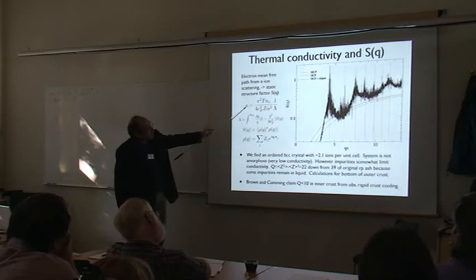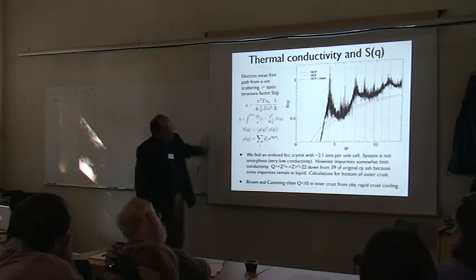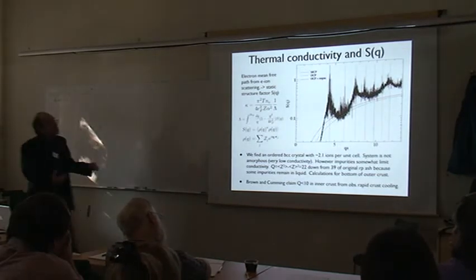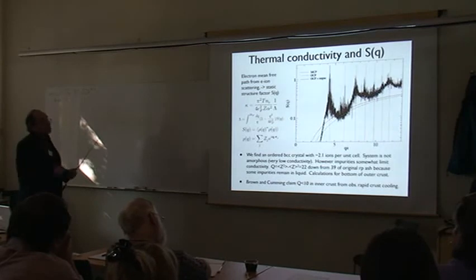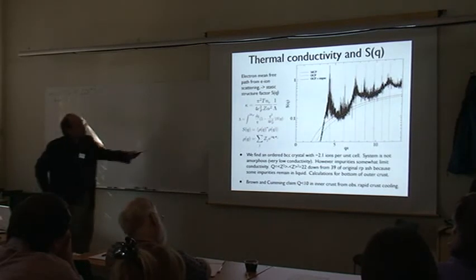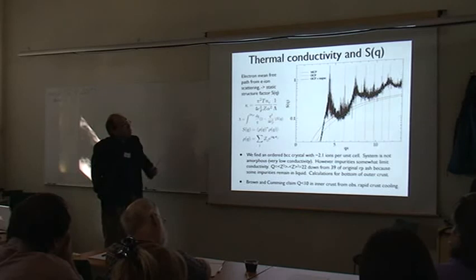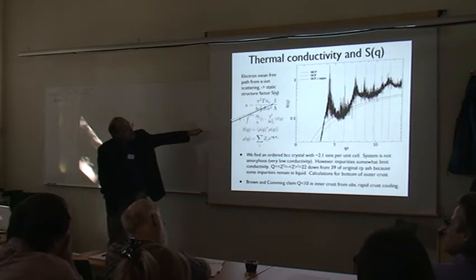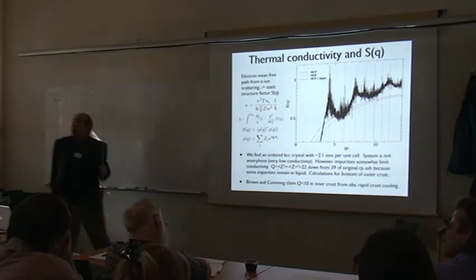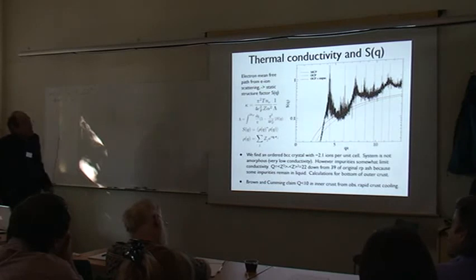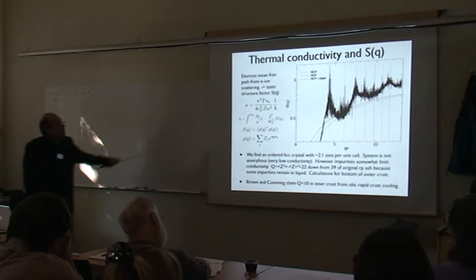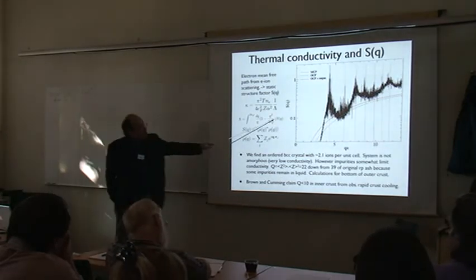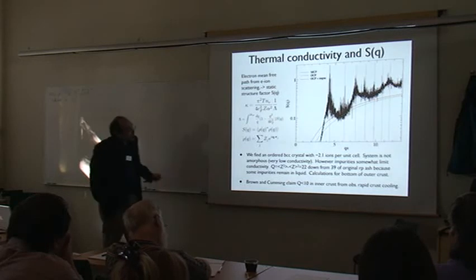So the thermal conductivity, in this case, we're assuming it's carried by the electrons. The degenerate electrons have relatively long mean-free paths. So the thermal conductivity depends on the density of electrons, and then it's divided by a Coulomb logarithm describing the electron-ion scattering, and that Coulomb logarithm is an integral over the static structure factor.